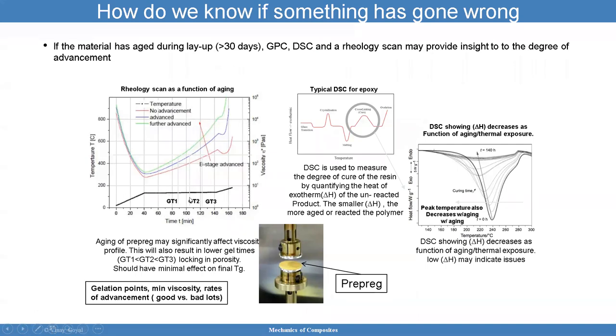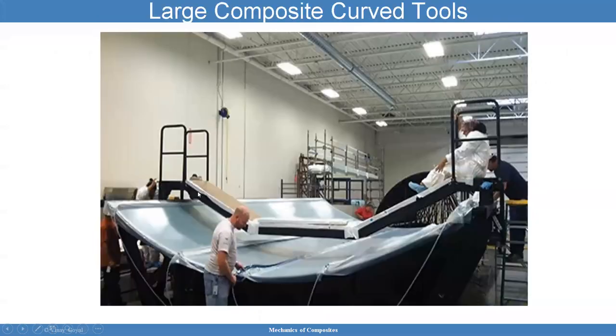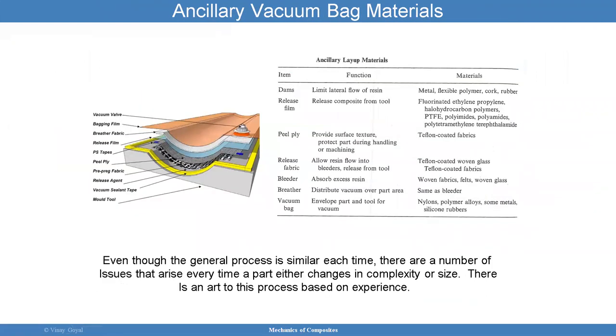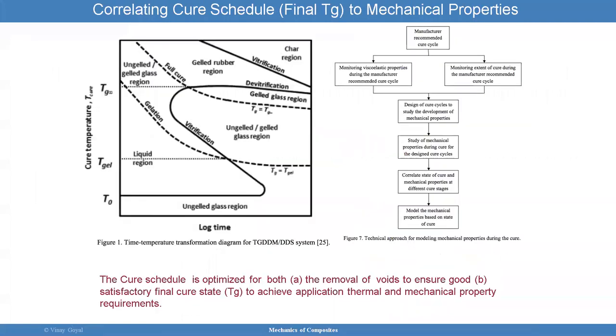Yeah, so here you can see some of that profile being shown. But I'll show one later to make it more clear. And then you want to make sure to correlate the degree of cure to the mechanical properties at different cure stages, because that helps you understand what's going on at the different stages. But also if something goes wrong, say that the oven turned off 10 minutes into the cure process, by having gathered all that data, you can study the impacts of that. And that is not uncommon, that the electricity goes out, or the autoclave runs into a problem.